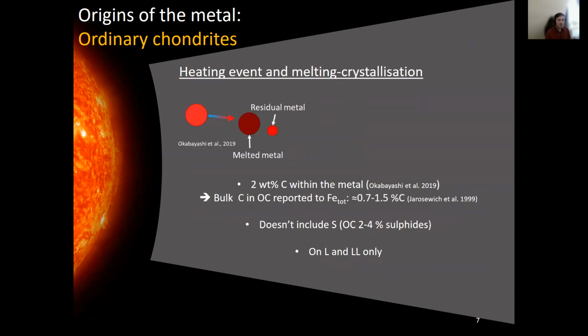However, more recently, another study contradicts this model, and on the basis of in situ analysis of highly siderophile elements, they suggest that metal signature is a result of heating event followed by melting and crystallization. However, that model proposed a value of 2% of carbon in the metal to reproduce the variations of composition, far from the total metal bulk carbon reported in iron, which lies from 0.7 to 1.5%. Also, their model doesn't include sulfur, whereas ordinary chondrite contain up to 4% of sulfides.